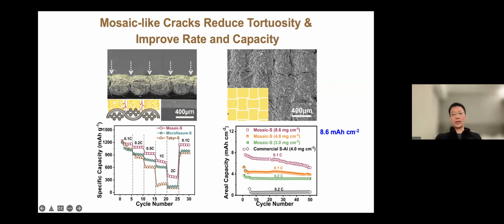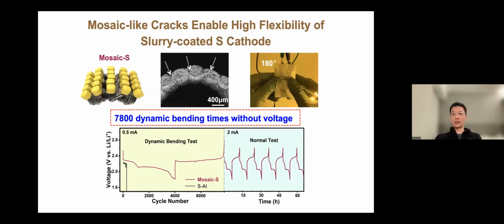And what we found is that these controlled cracks are actually good for flexibility, right? Because the entire sulfur electrode has already been chopped up into mosaic pieces, when the entire electrode bends, the bending stress can be released easily on the preformed cracks, and therefore no extra new cracks are generated during this bending process. So in our dynamic bending or ex situ bending, we don't see any issues with battery stability.